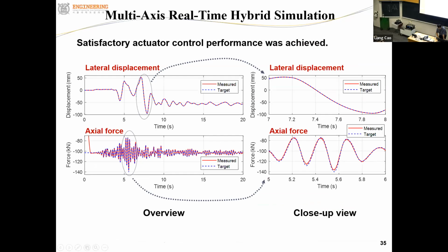The one here shows the lateral displacement, comparing the target displacement and the measured displacement of the bridge pier column. So we can see good tracking of the measured displacement following the target displacement, the displacement control. And this shows the axial force applied to the bridge pier column. Because we applied the vertical ground motion, the axial force is no longer constant. Depending on the vibration of the bridge deck, as well as the vertical ground acceleration, we have this kind of fluctuation of the axial force. So you can see good agreement between the target axial force and the measured axial force.